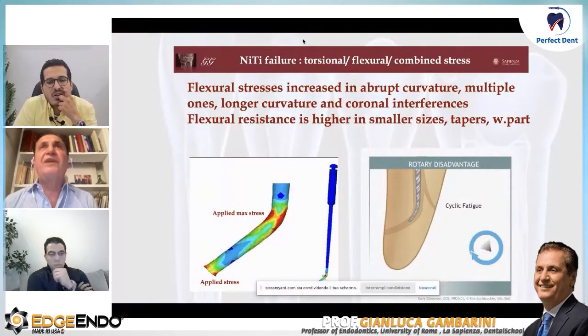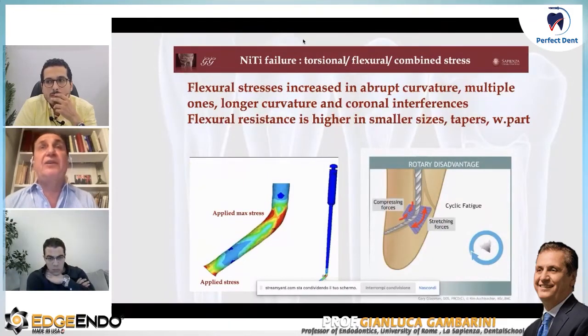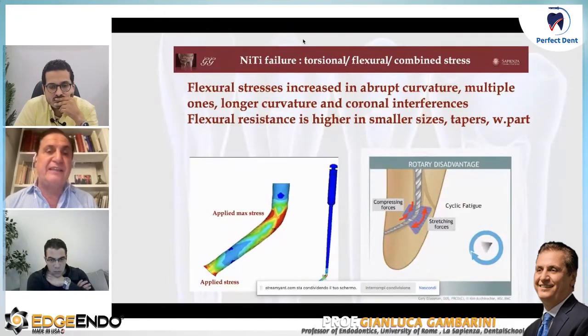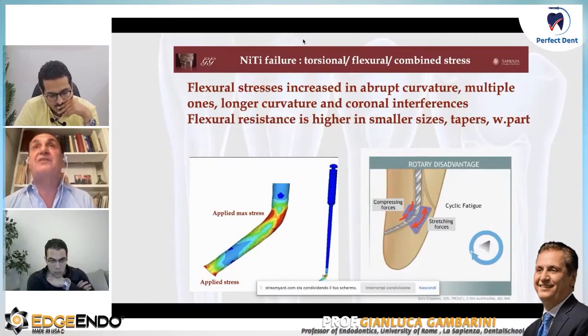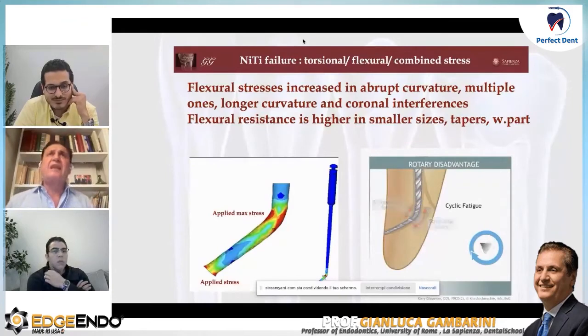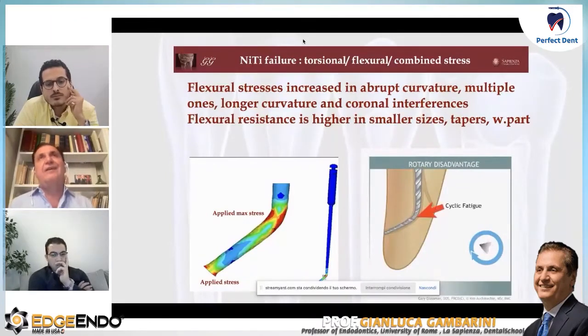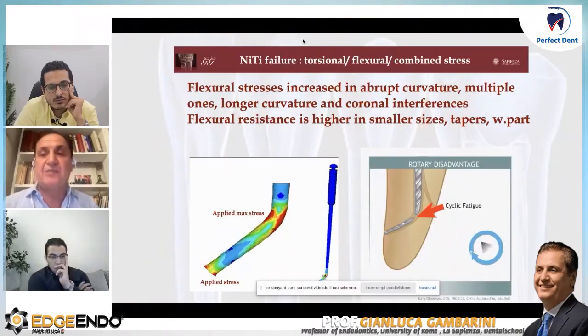Obviously, when we are inside of the curvature, we run the risk of breaking the file, and we know this is because of the high flexural stress. And we know that the flexural resistance is higher in smaller sizes, tapers and working part. So this is why X7 is perfect for this, because we are using 04 taper. We are using small sizes from 17 to 25 maximum, and we have a smaller working part with a maximum diameter of 1 millimeter.